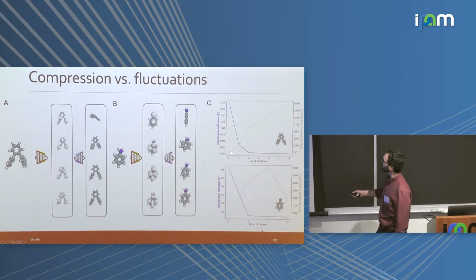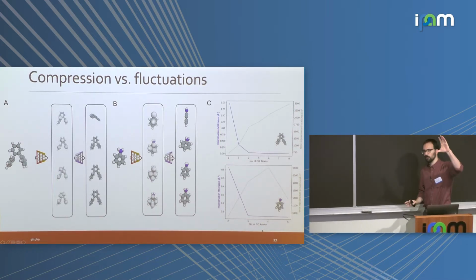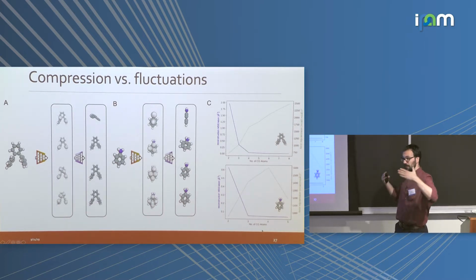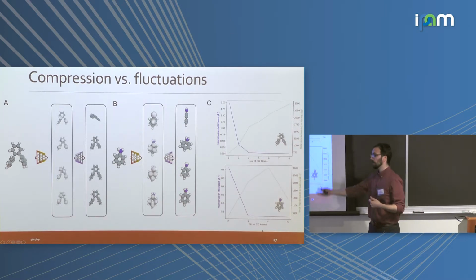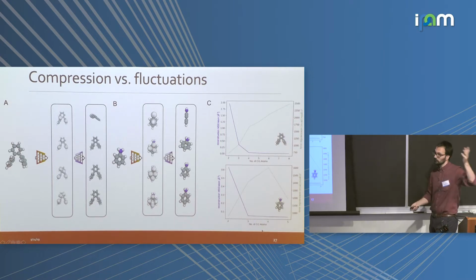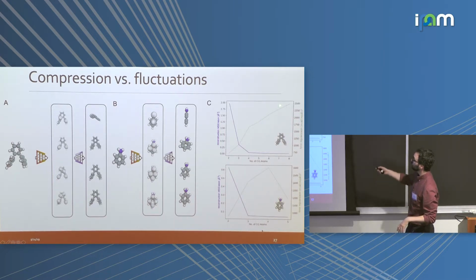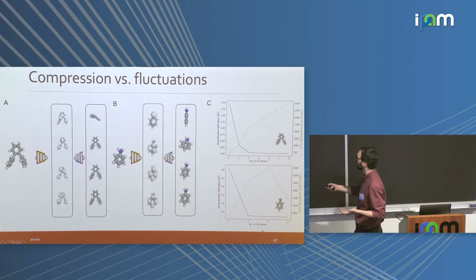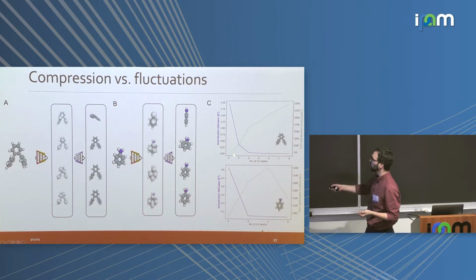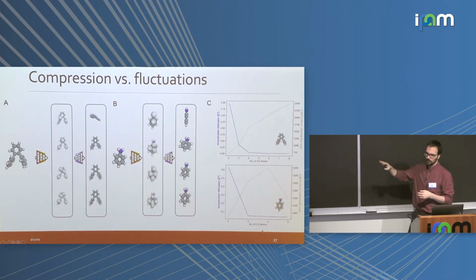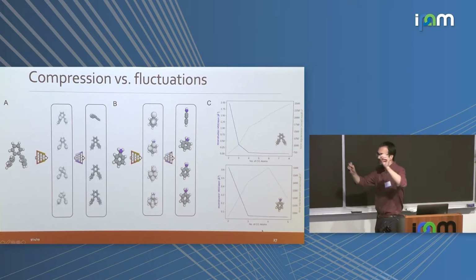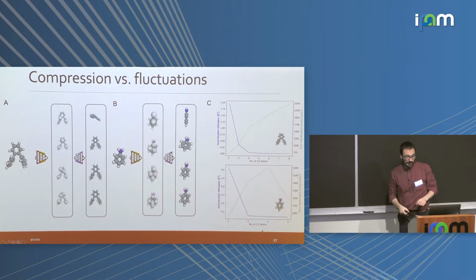But something that we also observe is the instantaneous force. I said that in the unsupervised part, we can learn a coarse-grain mapping, and without us training a VCG yet, just having a coarse-grain mapping means that there is an instantaneous force. This is the transformed version of the all-atom force. You can see how the instantaneous force gets higher and higher as we have higher and higher resolution, because we're not averaging out anything anymore. Here we were averaging all the motions, so we had a very smooth potential surface, and as we have more and more atoms in the CG representation, we see more forces trying to push all the atoms in all the directions.